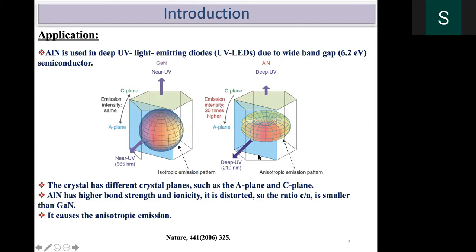The interesting thing is, since this aluminum nitride is anisotropic in nature, when you compare with gallium nitride, the C plane emission is much smaller than the A plane. The A plane can emit 25 times higher intensity compared to the C-axis aluminum nitride. So this is the very important difference between the gallium nitride and the aluminum nitride. And already I told that for aluminum nitride, the C and A planes are comparable with the gallium nitride C and A planes. So this can be a good substrate in the case of growth.